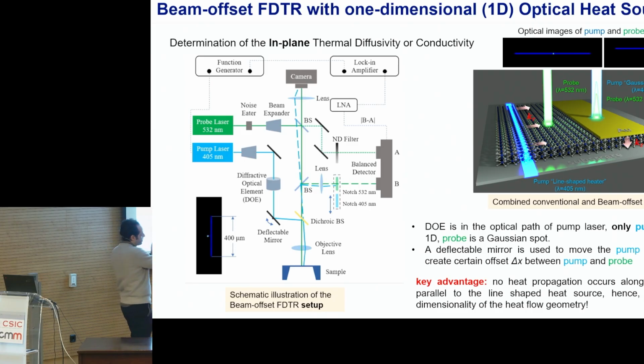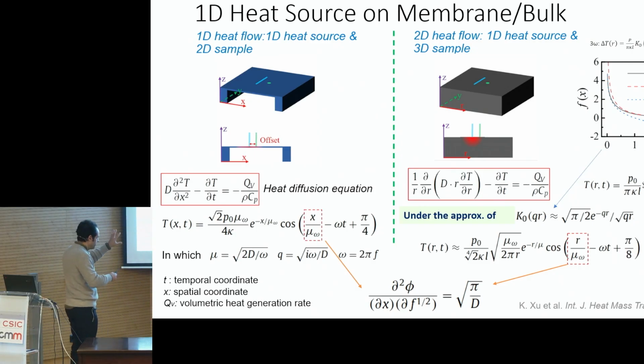And then on the right part of the image, you see a conventional frequency domain thermoreflectance, where we can measure, as usual, the cross-plane thermal conductivity. So by having this setup, we can know exactly the thermal anisotropy of the materials. And this is interesting if we really want to see the thermal transport characteristics of the materials that we would like to integrate in our devices, for example, in transistors. Okay, so I will not go into the details about the model. We also spent some time showing that this technique can be applied to 2D samples and also to 3D samples.